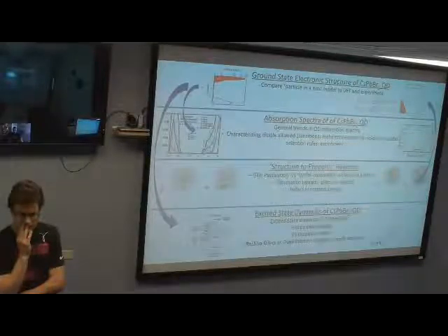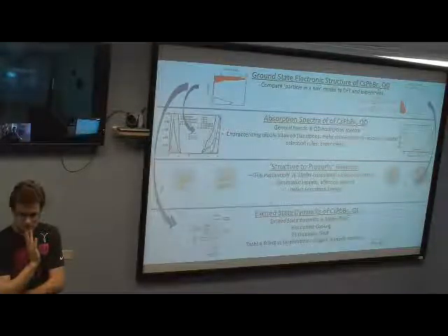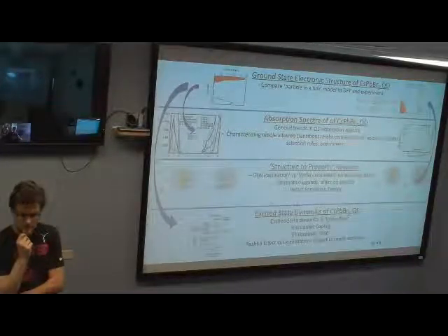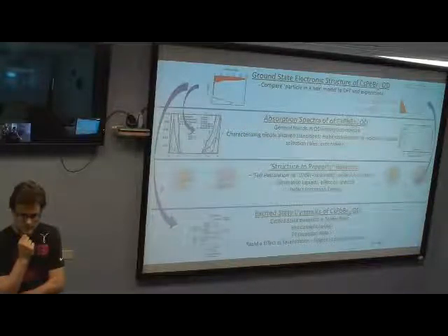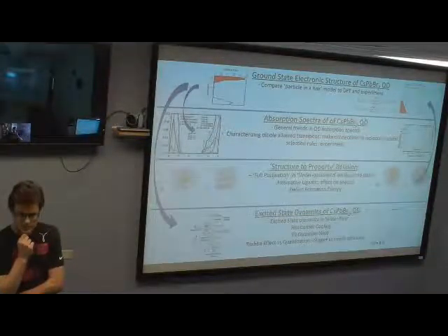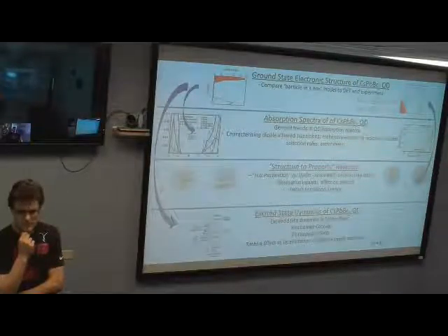So intuitively, the confinement should lead to even slower relaxation rates compared to the bulk materials, because you really increase the mismatch between phonon energies, which is usually small for inorganic materials, the low frequency vibrations, compared to the splitting between your electronic levels, which is definitely growing. You can estimate it based on your models to see what exactly the splitting between your levels is near the band edges. And it's exactly the same story for the semiconducting quantum dots. So people were expecting that the relaxation rate should be decreasing, slower than in bulk because of this confinement effect, because you have a much larger mismatch between the energy of phonons and the splitting between electronic levels when you go to quantum dots compared to the bulk materials. But experimentally, they don't see it.